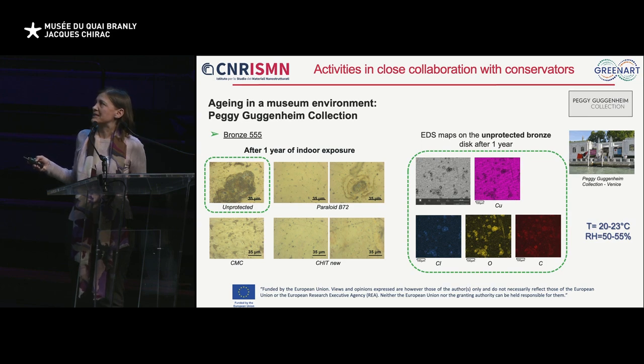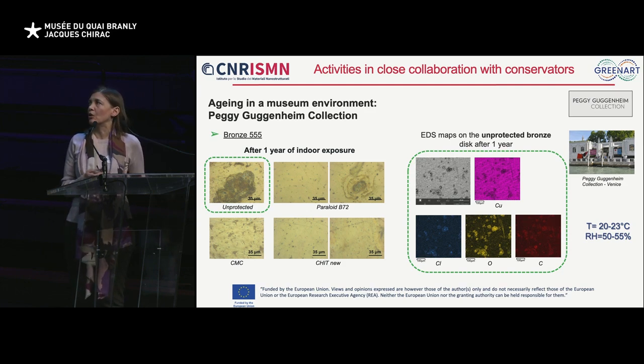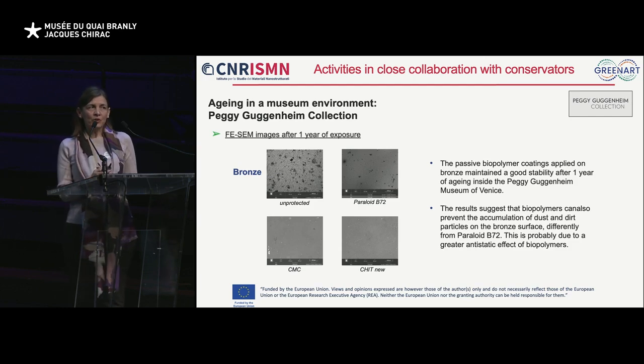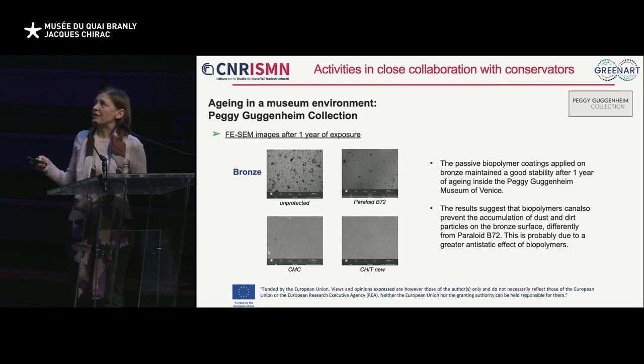We can also see the presence of some particles with a higher amount of carbon, so probably organic species. And we performed additional analysis by using scanning electron microscopy, and we confirm the presence of alteration products on the surface of the unprotected coupon. And it is interesting to observe the presence of a higher amount of particles on the mock-up coated with the commercial products with respect to those coated with the biopolymers.